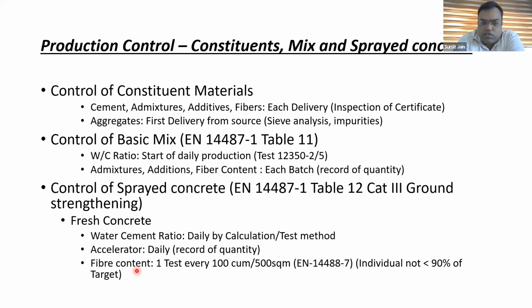Then next we go on to the control of sprayed concrete. There are various stages of shotcrete. In the initial young stage, which we also call the green shotcrete, the water cement ratio is calculated daily. The accelerator is checked daily, and for the fiber content, we do one test every 100 cubic meters or 500 square meters of sprayed application. In the fiber content, the individual sampling should have fibers not less than 90% of the target fiber dosage.